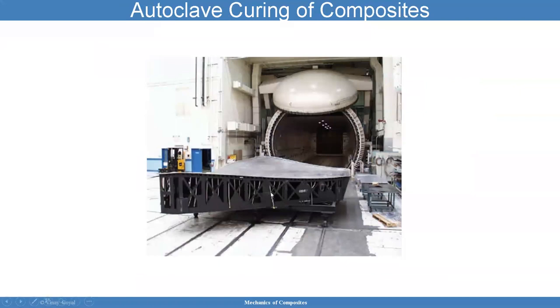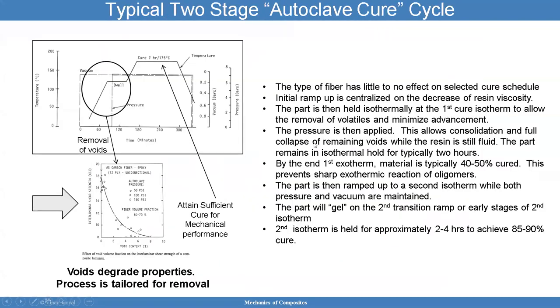And here was the part we talked about in the previous page when I showed you. So the type of fiber, and here I'm showing you a two-stage autoclave cure cycle. You can see here that I have vacuum and I have pressure applied. So you still have vacuum the whole time, and then you're applying pressure to some level, and then you also have temperature being applied. The bottom line is the type of fiber has very little effect on the selected cure cycle schedule.